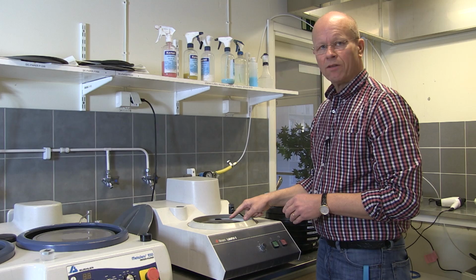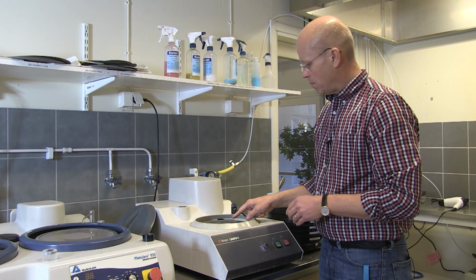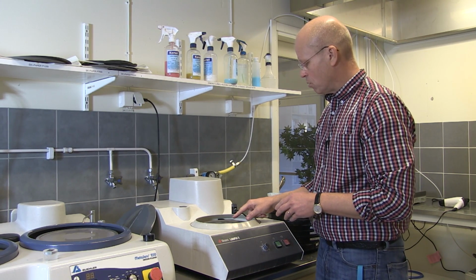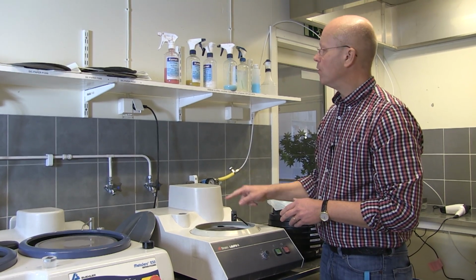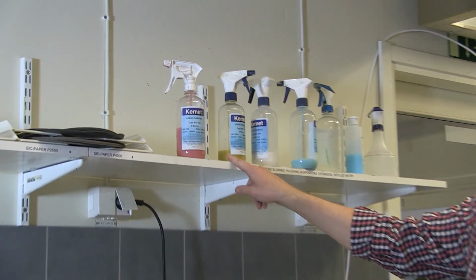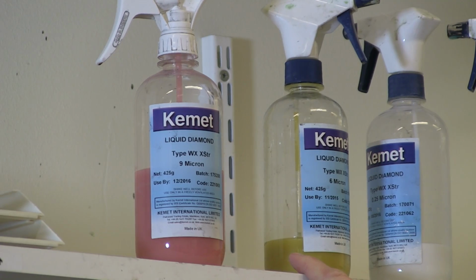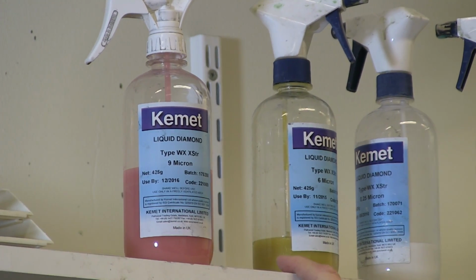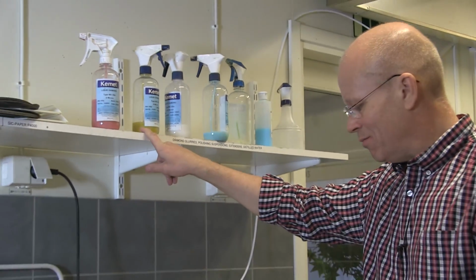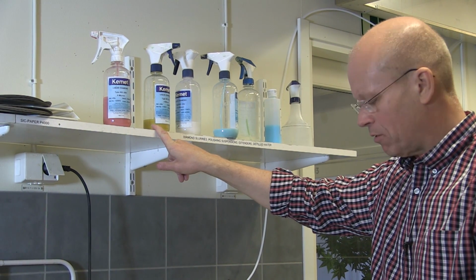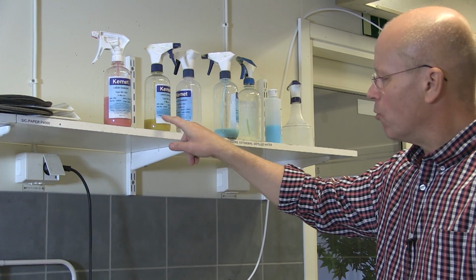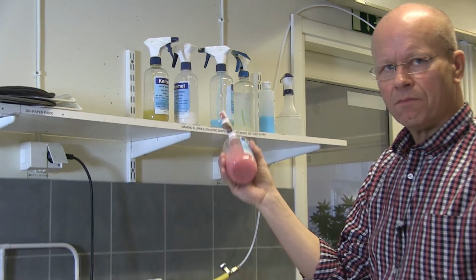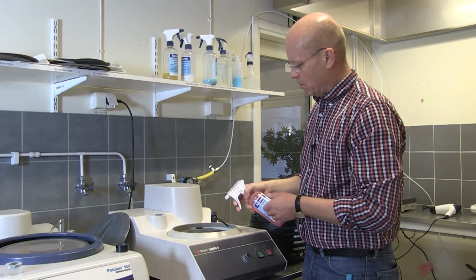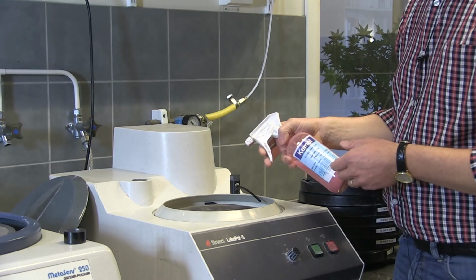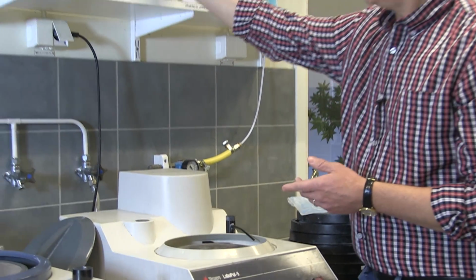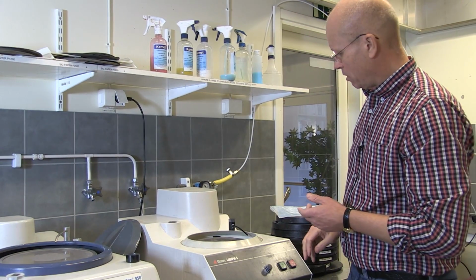Normally it's quite a lot of diamonds on the cloth, but if you need to fill up with more diamonds, you can find more of them on the shelf up here. But add more only when you see that no action is on the sample, not much is happening. Then on a rotating cloth, add 1 or 2 more sprays. I will show you that later on too. So now I start polishing on the first step.